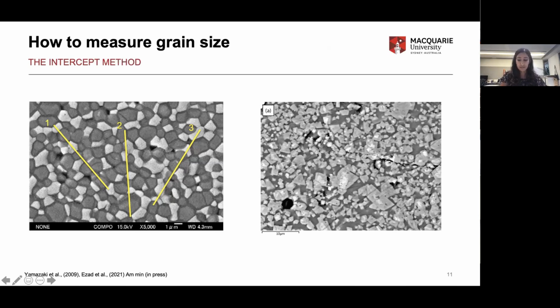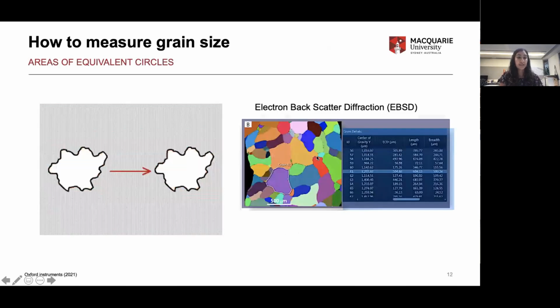The other really common technique is the areas of equivalent circles method. And this one's even more popular. Over 700 times this has been published in the past 5 years. And for those of you that often turn to electron backscatter diffraction as your method of grain size analysis, this is actually what's going on in the background. So you would draw around all your grains, following their grain boundaries very carefully. And the area of this grain is converted into a circle of equivalent size. And then we can get the diameter in this way.